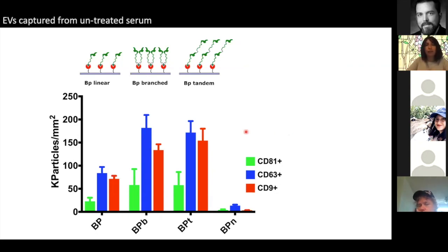And in this case, surely the specificity of the capturing and the affinity is not as good as when you use a highly purified sample, and I think this is really normal, expected. However, what I'd like to underline here is that when we use the multivalent presentation of the peptides, so the branched or the tandem configuration that you can see here, the specificity and the affinity of our capture really increase, demonstrating an important role of multivalent presentations, especially in complex samples.